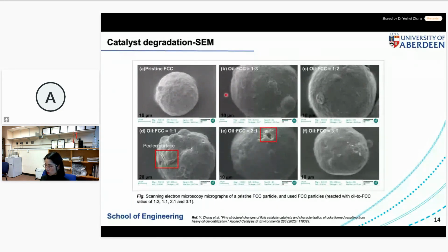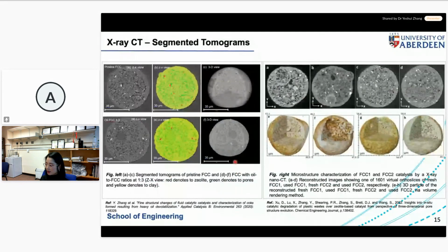And I tried to simulate the degradation process of this FCC catalyst through a small chemical conversion process. If you look at the surface of the catalyst particle, you start seeing some defects, and something being formed, or the surface of this catalyst has been damaged by the thermal process, or peeled off. It's powerful to use SEM to see the surface, but we want to identify the internal structural change of this catalyst particle.